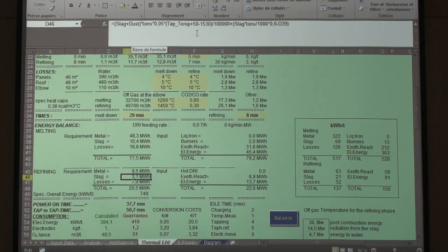In the ladle furnace, it is not exactly the same, because most of the time the slag is colder than the steel. Why? Because you have a lot of air ingress, which is cooling down the slag on top. So the slag is warmer in the area of the arc, but outside it is much colder.